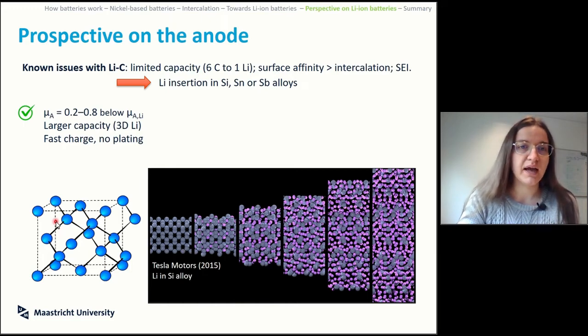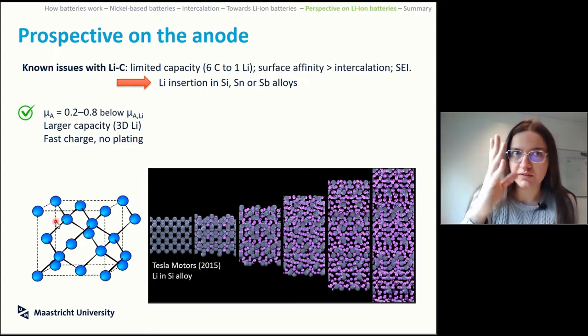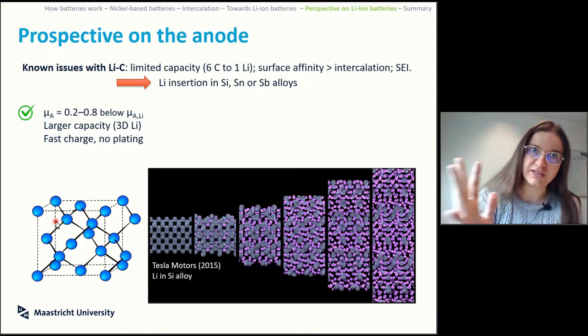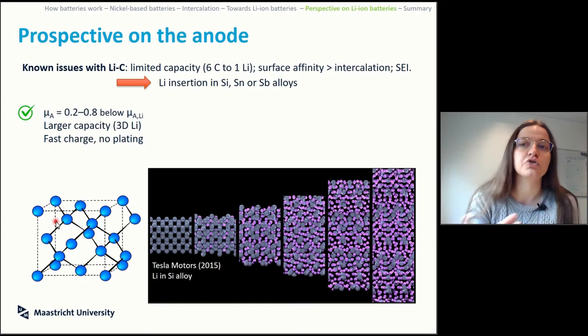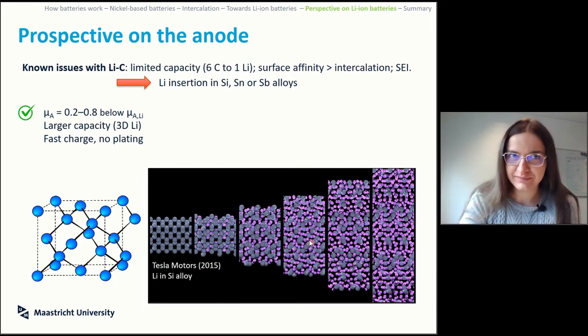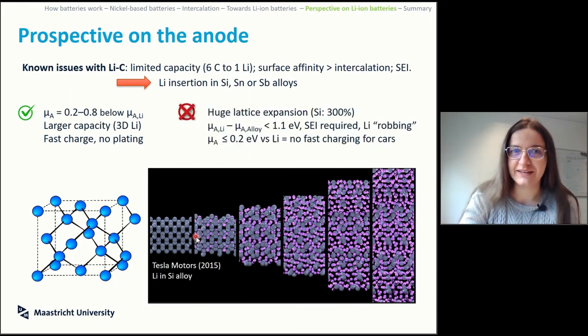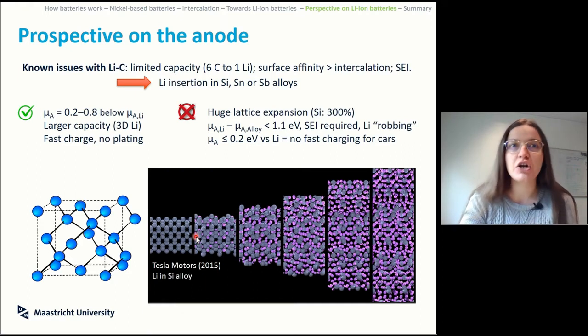And it will have a very large capacity because you should be able to put a lot of lithium inside, and since you don't have the plating, so you don't have the lithium that goes first on the surface and then more slowly inside, the charge should be faster. This has been explored by Tesla some years ago. The main issue, as you can probably guess by the image here, is that this thing has a huge lattice expansion, like enormous lattice expansion.